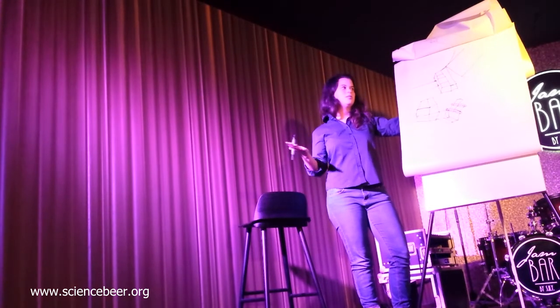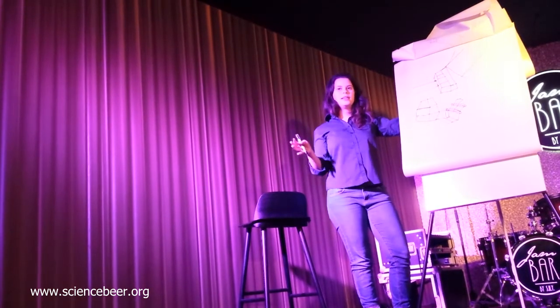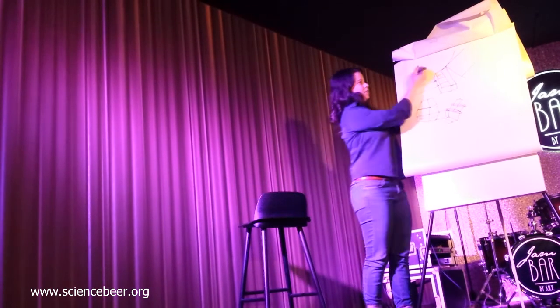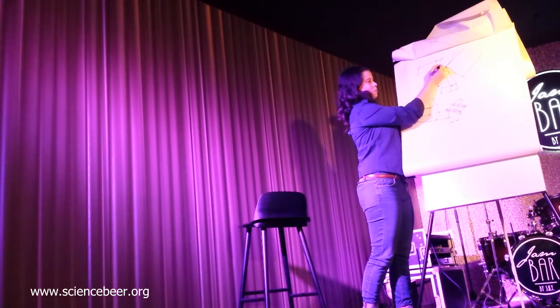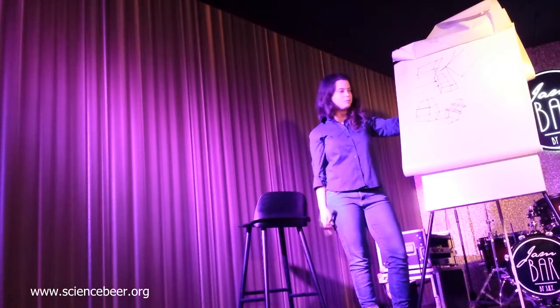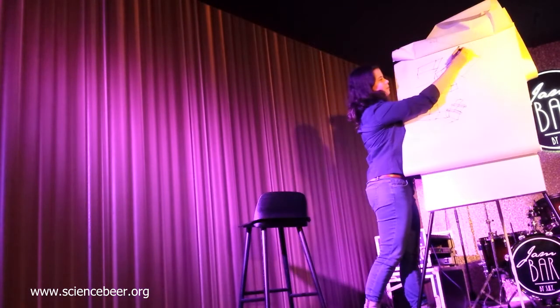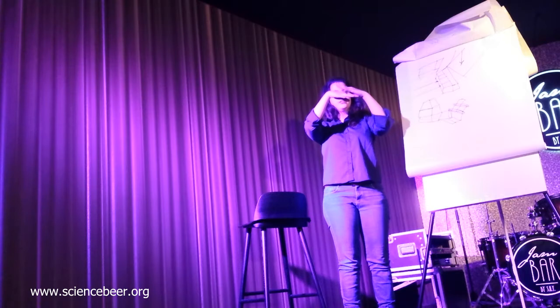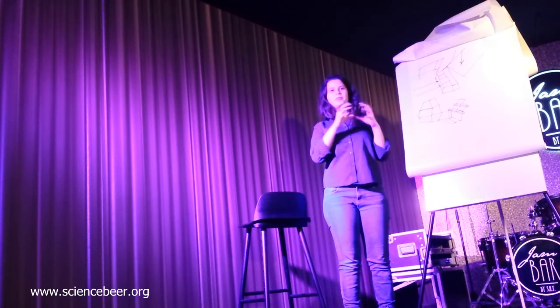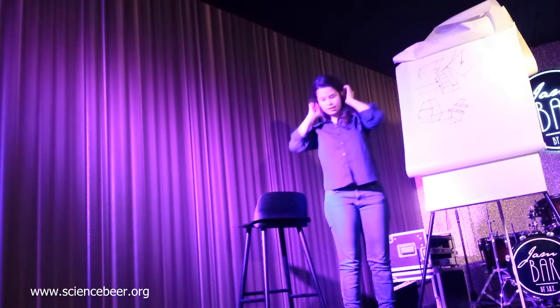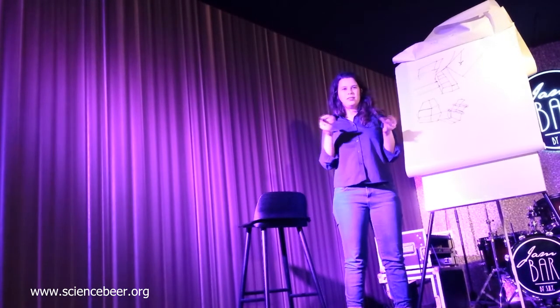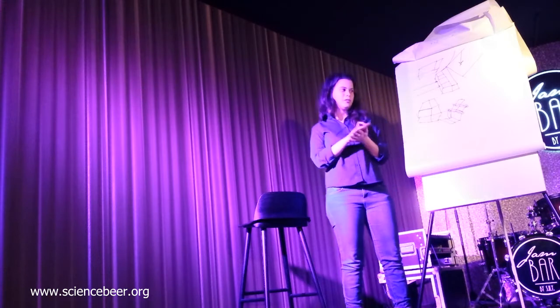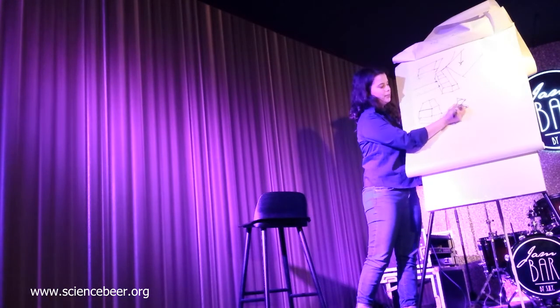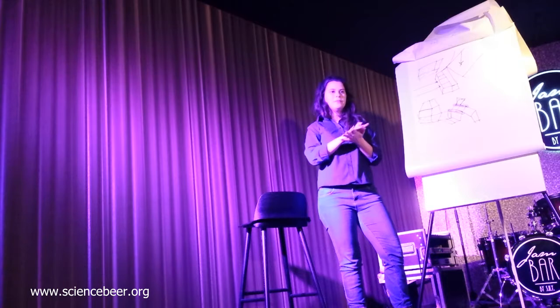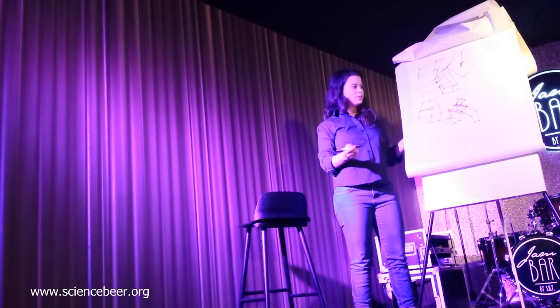At the moment, there's no way, using regular printing, to make single crystals. And a single crystal is this very smooth, perfect channel where you can get the maximum speed out of it. What we try to do is apply a force here. So we have our blade here, our material, and when you get a bottle of water and you shake it with something inside, it all mixes up and dissolves if there's a type of precipitate inside. In the same way, these little precipitates, or pieces where the solution has too much material, or is supersaturated, create these little boundaries, crystals that go everywhere. We want to mix them with our shearing, with our printing mechanism, in order to make them more continuous.